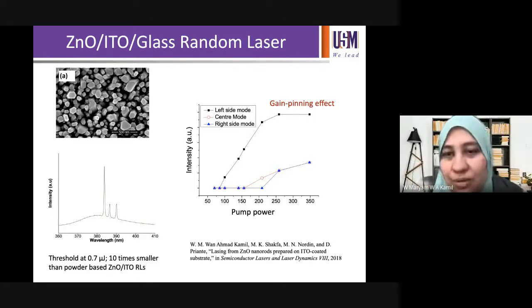And we notice that when these two modes start to fight for the gain, we see a gain pinning effect. This means the intensity is at the same level. Now, gain pinning effect is not something that is observed in random lasing. It is something that is observed in conventional lasers.